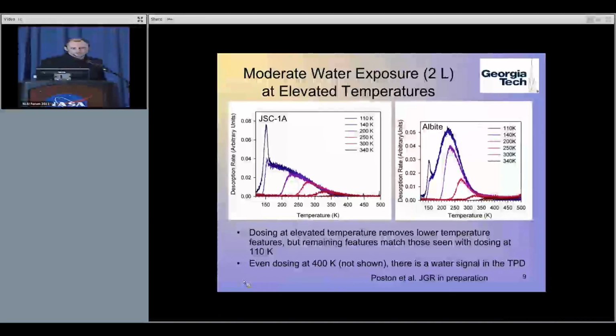So I've been claiming that this is water chemisorption and not some sort of tortuosity problem, and this is the experiment we did that causes us to believe that is probably the case. If we look at the left graph, these temperatures up here represent the temperature at which I exposed the sample to the water. So if I dose the water at 200 Kelvin and then pump any remaining water out of the chamber, cool to 110, and then run the experiment just like I do in all the other cases,